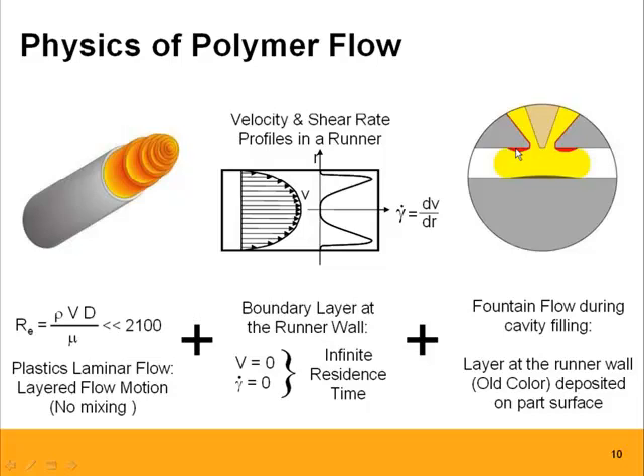So most of you probably know if you do a color change, the actual color on the part changes over usually very quickly. It doesn't take only a couple of shots even if you change from black to yellow, but on the surface, sometimes for a very long time, you keep seeing the old color. And the reason for that is the laminar flow of the polymer.